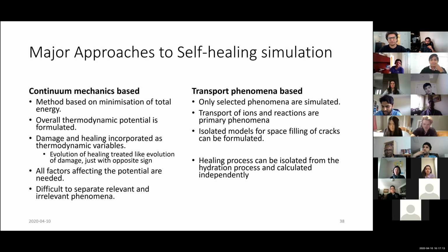Basically, the sorptivity is going to change if there is a crack, and if the crack starts to get filled. But if the crack is a little too wide, then the water will not rise up because there won't be enough surface tension. If that single crack is too wide, then we won't see any difference in sorptivity. To go back on this, while Obina was suggesting this, there are internal cracks inside the concrete. There is no single crack that is very wide while we are below the ultimate strength.